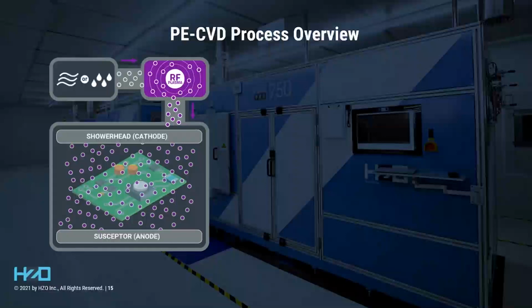Plasma can be generated remotely, as is illustrated here, or inside the chamber with the product if it's between two electrodes. Plasma activation of the species allows a very wide range of chemical precursors, silicons and silanes, hydrocarbons, fluorocarbons, oxides, and a limited range of metallics. Tuning the plasma parameters, as I mentioned before, such as frequency, power, electrode spacing, can also allow you a wide range of film densities and chemistries.